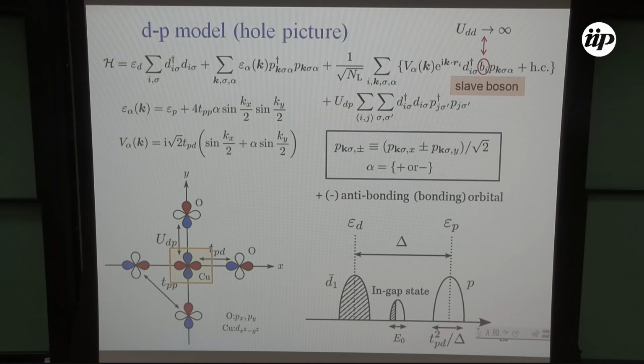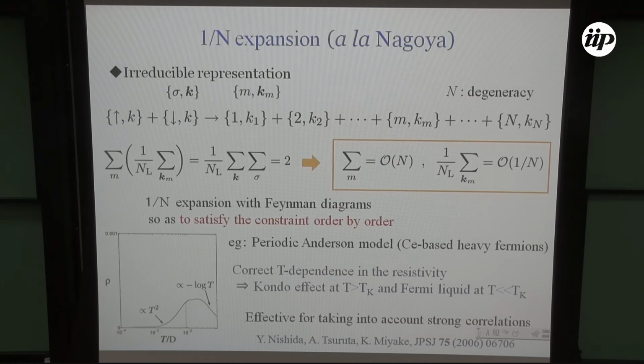We discussed the charge transfer processes in high-Tc cuprates. We use this kind of dp model with the hole picture, introducing the slave boson to eliminate the doubly occupied state of the d electron. Then we also take into account tpp, tpd and Udp like this. Due to the direct hopping, there are two bonding and anti-bonding p bands here. So this is the 3-band Hubbard, 3-band dp model. Using this 1/N expansion, this is very effective for taking into account the strong correlation effect.